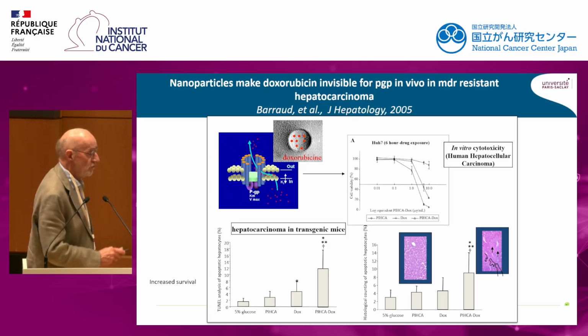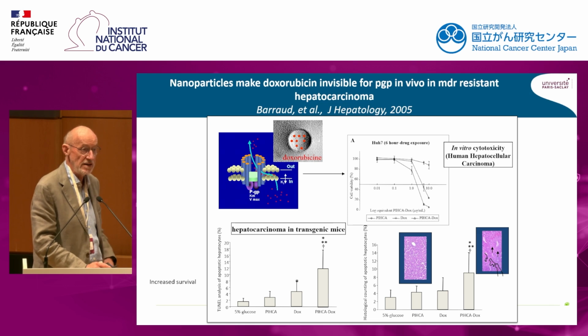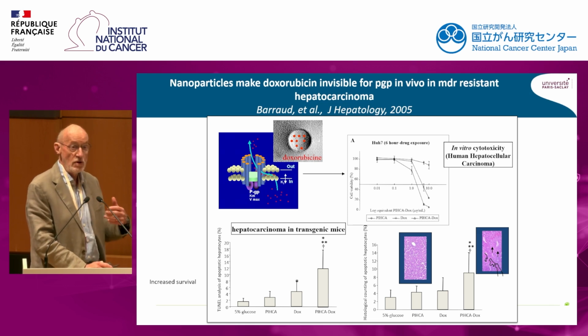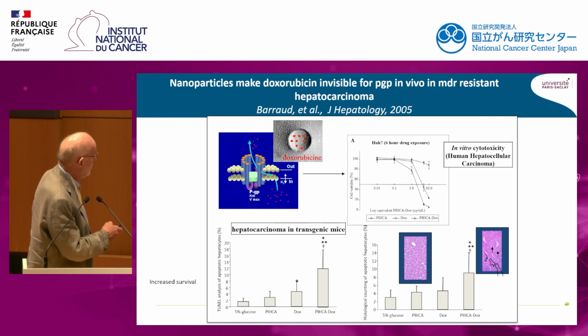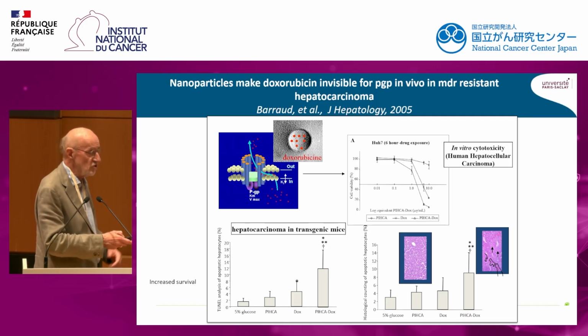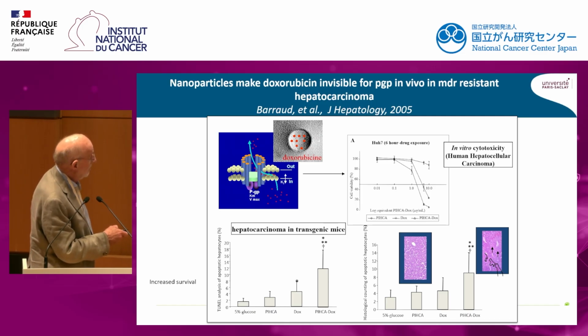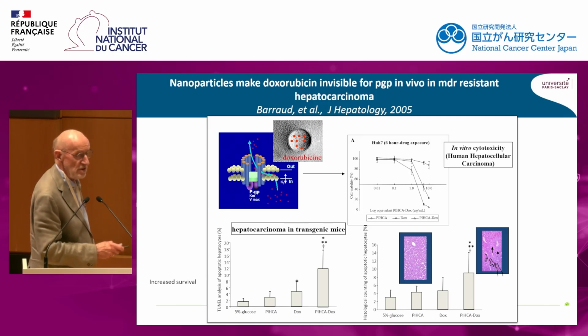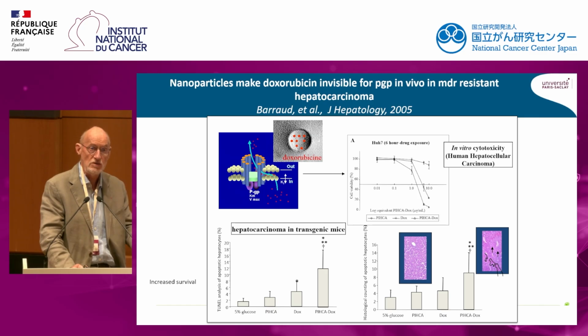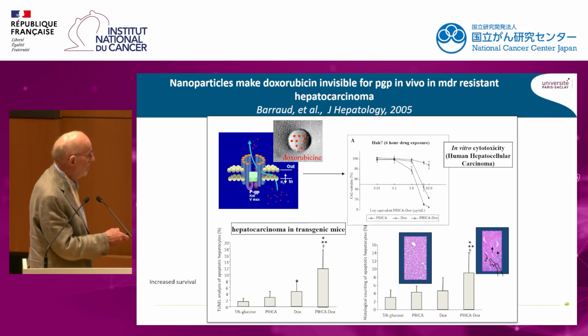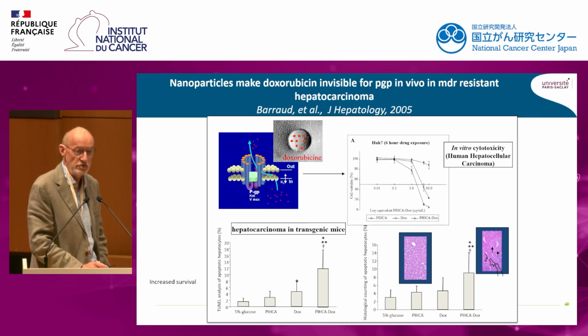And then, of course, we moved in vivo in preclinical cancer models. In general, we observed an increase of the survival because of this modification of the biodistribution. A typical example here is the use of a model, a hepatocarcinoma in transgenic mice. And you can see that after administration of the doxorubicin loaded into those biodegradable nanoparticles, there was a huge increase of the apoptosis of the cancer cells comparatively to the treatment with the doxorubicin as a free drug.